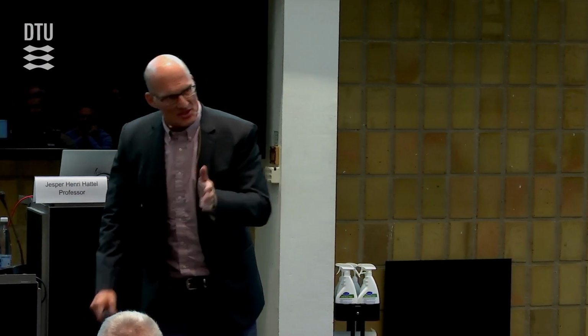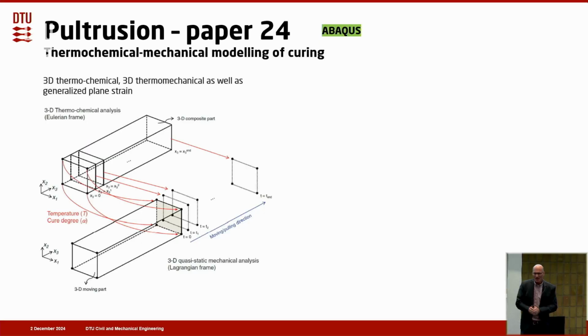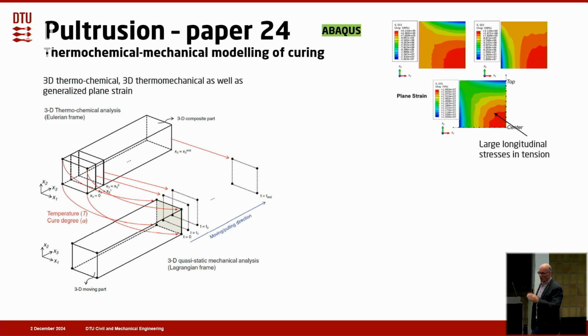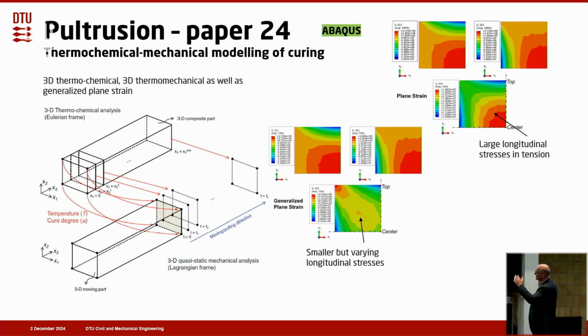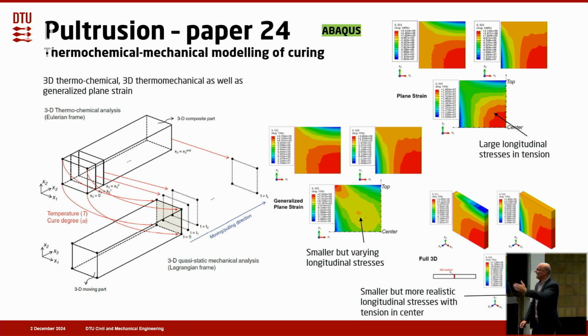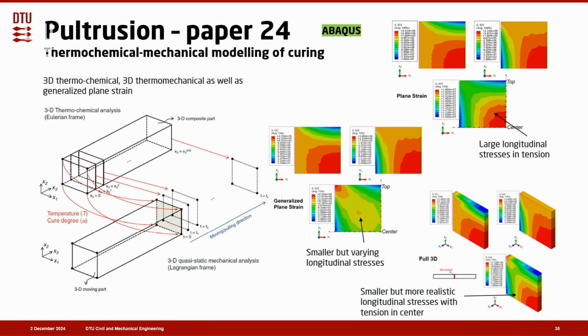Then we continued and said, okay, well, this was a plane strain. A plane strain assumption means that you get longitudinal stresses that are very high because they're constrained. So we looked at a generalized plane strain as well as a 3D model. This is what you see here. This was a plane strain. You get very large longitudinal stresses. So we looked at smaller but varying longitudinal stresses in generalized plane strain. And then we went to 3D. And here are smaller but more realistic longitudinal stresses with tension in the center. So if you want to look at not only in-plane stresses but also longitudinal stresses, the 3D model is probably preferable.